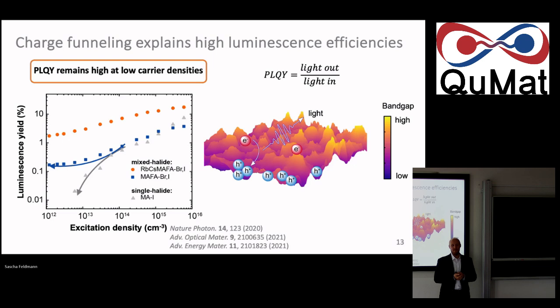Maybe a related question. Since you have all these inhomogeneities, is it really fair to talk about the crystal, or should I think about it as very small crystals that happen together? Yeah, these are definitely polycrystalline materials. The grain size for these might be 200 nanometers or so, little crystalline domains. And even then I wouldn't really call them single crystalline domains, because they're not. This is essentially polycrystalline. One can also do such measurements on mixed halide single crystals, but that's another story. So these are polycrystalline and partially locally demixed in the halide composition, and it modulates your charge carrier dynamics quite a bit, but not fully detrimentally, which was nice news, right?